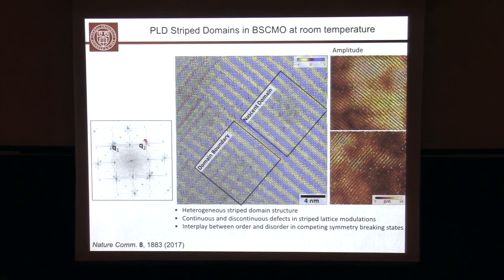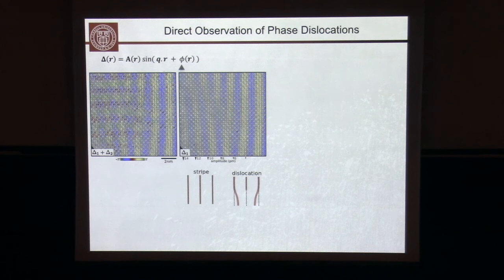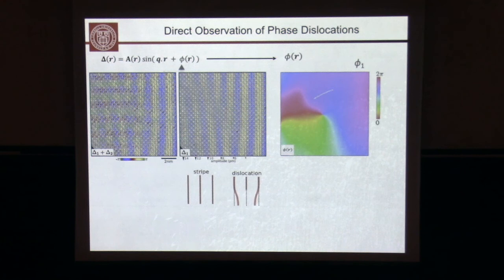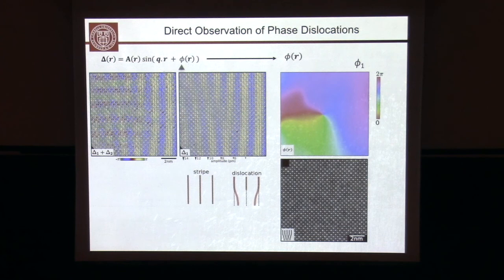And so from this picture of the domain boundary, we can look specifically only at Q1, one of the order parameters. And what you see, if you now carefully look, there is an additional stripe that starts here. So that picture is that of a dislocation or a topological defect, if you prefer. And the way you see that is by extracting the phase of the modulation. And the phase now shows a 2-pi phase wrap as you go around this topological defect. Now, what's important to realize is that this topological defect or dislocation is only in the modulation field. The crystal lattice is clean. There are no actual crystal defects. By the way, the modulation you see is due to doping.